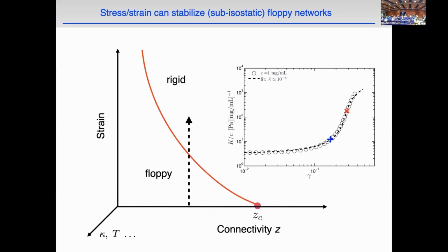Now, I mentioned that the volume fraction is a 1/10% volume fraction, 10 to the minus 3. It's not a coincidence that there's about 3 orders of magnitude of stiffening here. And that's because the naive dependence on volume fraction for a fully stretching regime would just be that the modulus would be proportional to concentration. For the bend regime, however, it should go like the concentration squared.